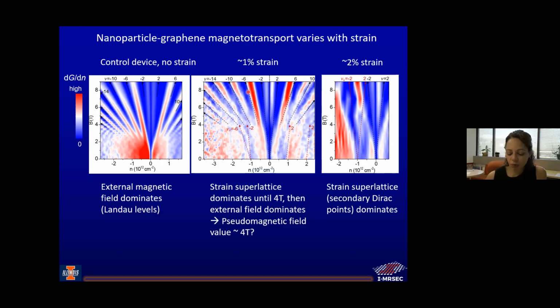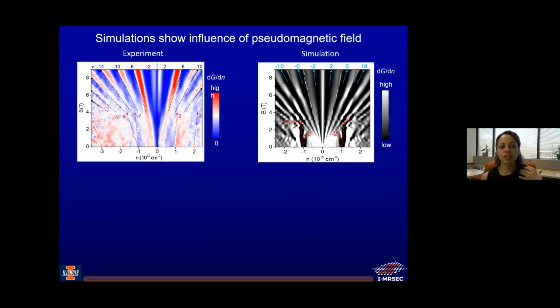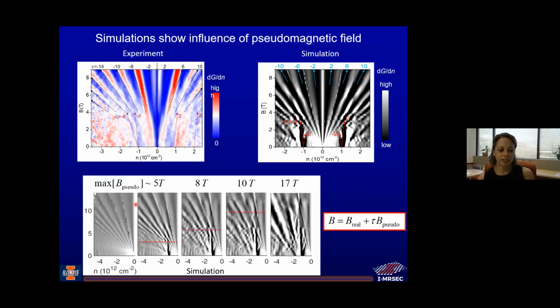Okay? And indeed, when we worked with the theorists to simulate this behavior, these simulations look very similar to what we have, but the simulations assume a relatively high pseudo-magnetic field. And in fact, you can see the simulations here. This is for no field, and it's just a standard fan diagram. And then as you go to higher fields, you get these regions like we have of interrupted Landau fans. And so the behavior we see is something similar to something like an 8 Tesla pseudo-magnetic field on average across our device.